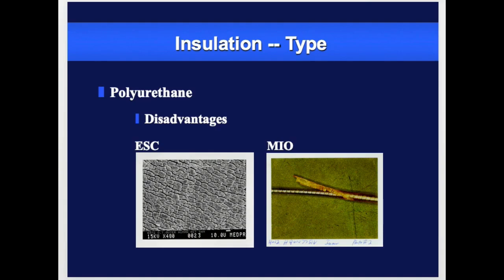Here, the body's natural defense against the foreign object produces cells, macrophages, cells that produce peroxidase. The peroxidase migrates through the polyurethane. You can see in this picture that the oxygen molecules from the peroxidase mix with metal ions from the conductor. This mixture works to oxidize the polyurethane. In this example here, metal ion oxidation has occurred to the point where the polyurethane insulation has completely oxidized and broken away from the lead.